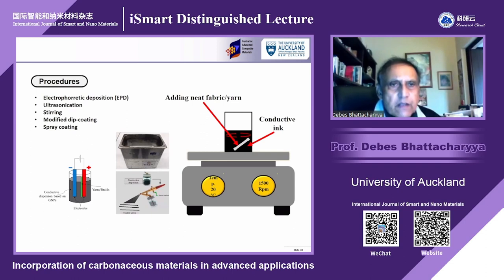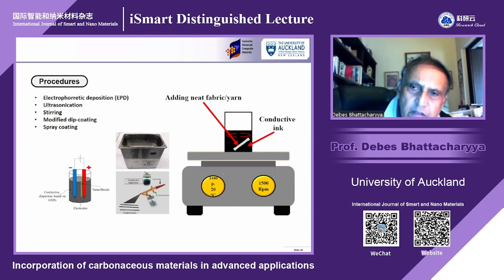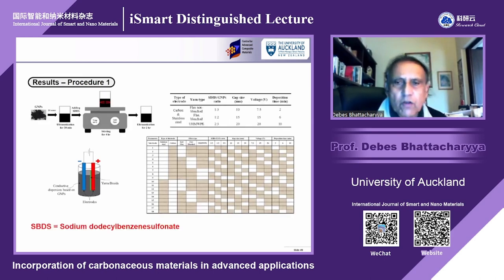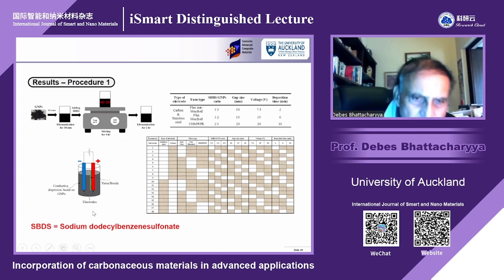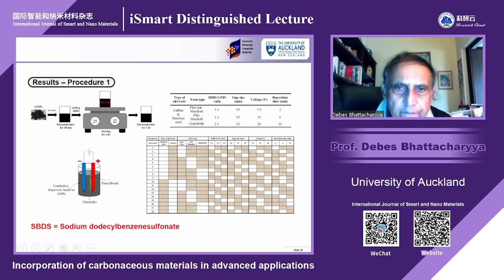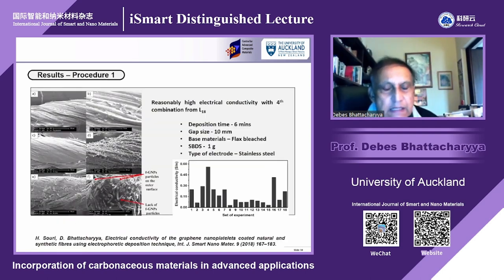Typical procedures include electrophoretic deposition, ultrasonication, stirring, dip coating, spray coating, all sorts of things. Instead of going through the detail of how we controlled temperature, the left hand side was 20 degrees centigrade, 1500 RPM, and we dipped. It is time consuming. You have to allow this, and the conductive ink, you can see it is dipped. I'm not going to explain the whole Taguchi table, but one thing we can say is that we also added some sodium dodecylbenzene sulfonate, SDBS.